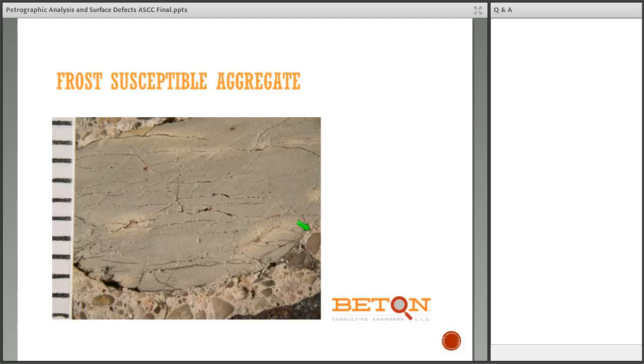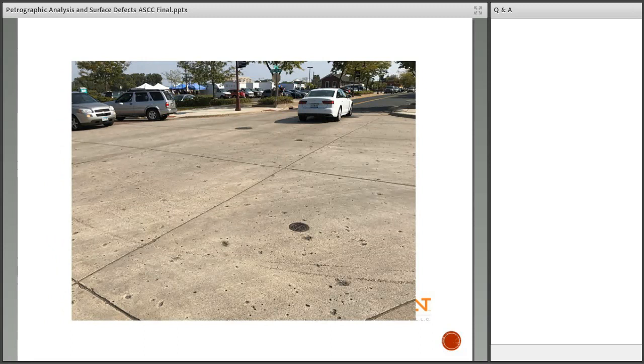And this is what frost-susceptible aggregate looks like. This is exhibiting what we typically refer to as a shattered pattern. Basically, the aggregate is shattered, and those fractures will extend into the paste and into the rest of the concrete and propagate towards us from a D-cracking issue in Iowa.